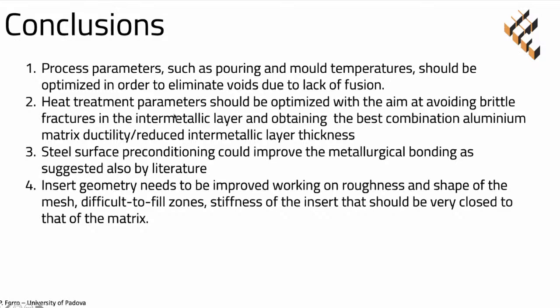We can also investigate or optimize the parameters of the heat treatment in order to reduce the thickness of the intermetallic layer. We can also try preconditioning the surface of the steel insert, for example, using copper coating or other material coating. And finally, last but not least, very important in my opinion, is to modify the geometry of the insert in order to avoid such lack of filling defects.